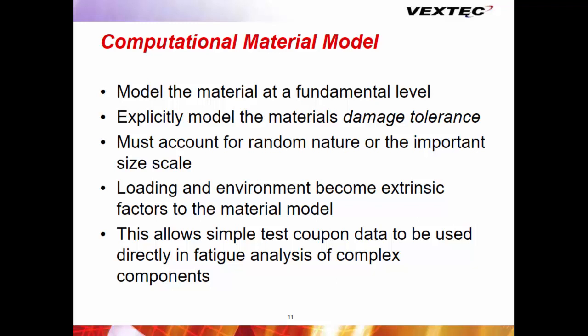But using this, we can go back and look at our test coupons. We can take data from the test coupons, not just the end life, but look at the fracture surfaces and understand where the crack started from, and we have that now. We have automated methods to put our specimens in these little RoboMet type systems, and it'll go through and scan the fracture surface for us and give us that. We've got a lot of methods out there that can automate this.